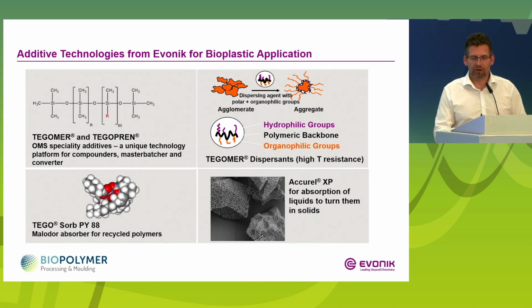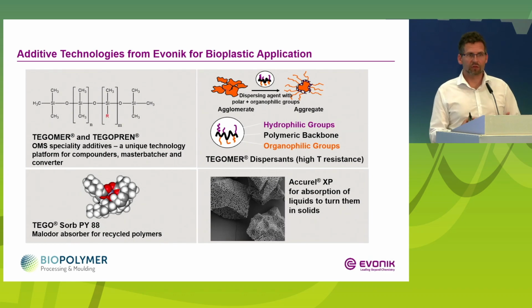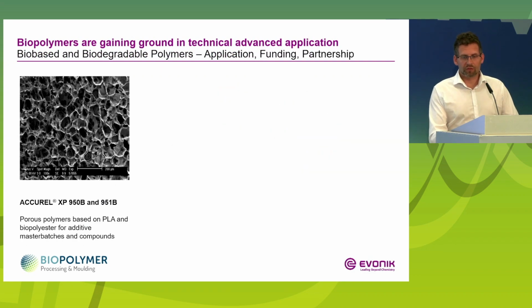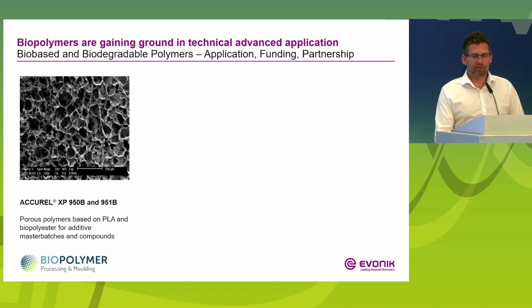this is not one polymer, so we have a portfolio of a wide range of polymers, and the specialty is that we can produce, based on these different polymers, master batches out of liquid additives to turn them into solid ones. And this is the first overlap with the bio-based or the bioplastics topics. Here we offer 2 grades, which are based on the one hand on PLA and on a biopolyester. And for you as processor of biopolymer materials, if you want to add an additive and it's liquid and you want to turn it into a solid one, because a solid one is more easy to feed, we can offer you to turn this special liquid additive into a solid one based on these materials.